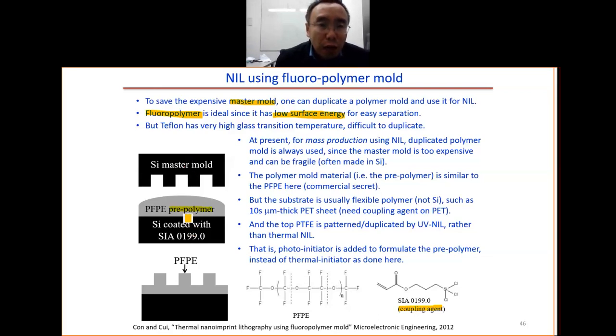Then you press the mold onto it, then you do a thermal process, you anneal it at a high temperature, then it becomes annealed and solidified. Then you get the mold. But this is what was published in this work.